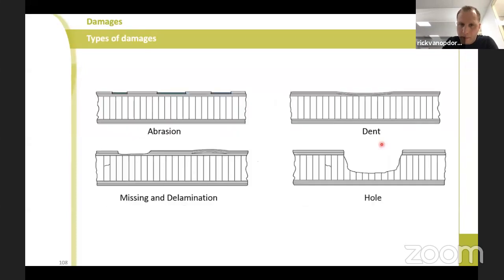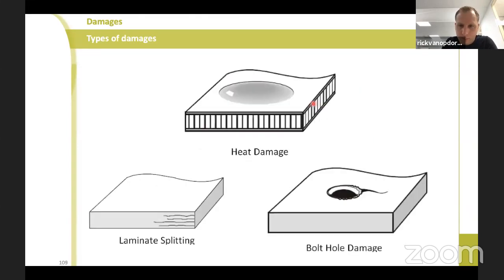So piece missing, delamination, see here, it goes up. So a delamination you can see with a flashlight and when you clean the part. And here we have a hole, this piece missing is very good visible. And we have a dent again. We have bolt hole damage, laminate splitting. So this in the material itself. And we have heat damage from a lightning strike.